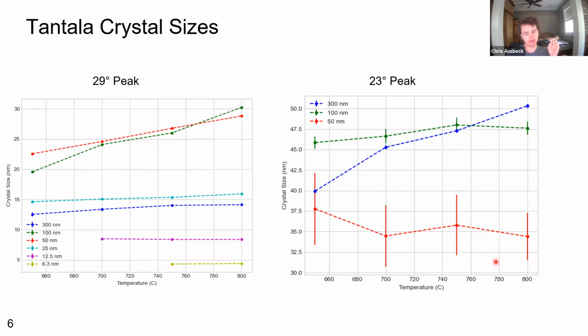So what's interesting here is that the crystal sizes never actually reach the layer thickness. They are always somewhat below the actual layer thickness. They never cap out.